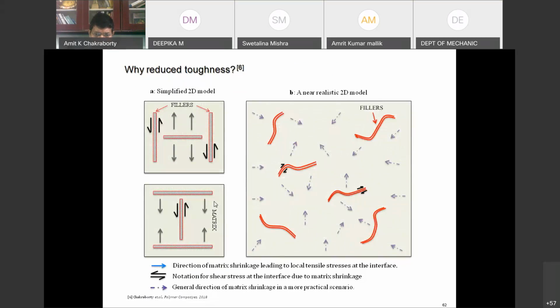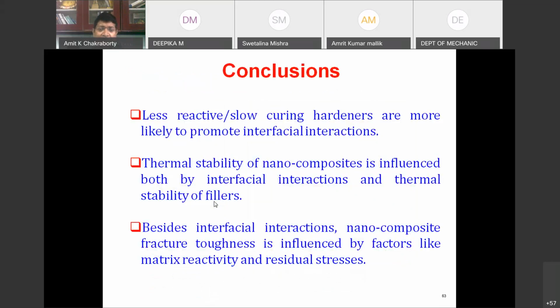So the conclusion of this study is here. What we have observed is that even with the graphene oxide, the butylamine modified graphene oxide fillers were slightly better in terms of enhancing the interfacial interaction with the polymer, with the epoxy resin. However, since we have studied two separate systems, one with fast curing, one with slow curing, we found that the improvement of graphene oxide modified with amine group was more prominent with the slow curing system.